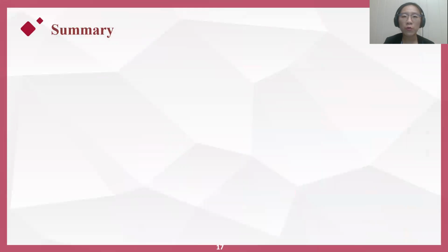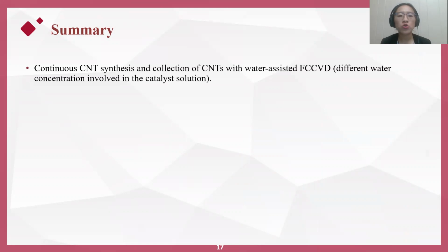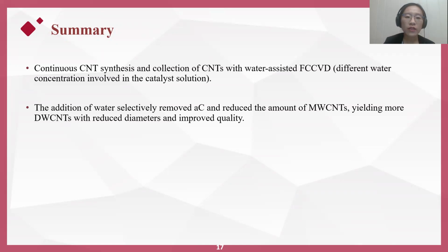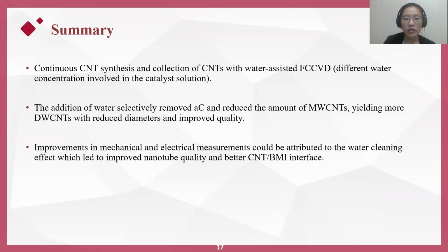A quick summary of what we have learned so far. We were able to achieve continuous CNT synthesis and collection with water-assisted FC-CVD. And the addition of water helped us to selectively remove the amorphous carbon layer and reduce the amount of multi-wall CNTs in the product, yielding more double wall CNTs with reduced diameters and improved quality. The mechanical and electrical improvement